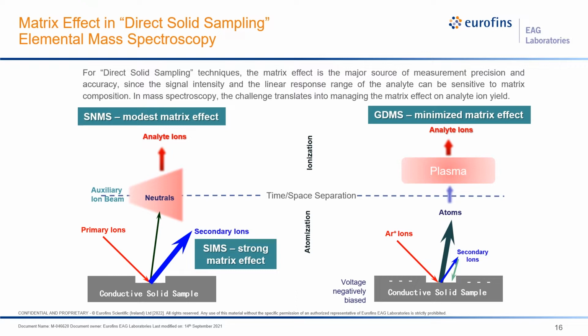Here are the three scenarios. The first case is SIMS, which uses a primary ion beam to sputter a sample and collects the secondary ion yield. As you can imagine, because the ion signal is directly generated from the matrix itself, it generally shows a strong matrix effect. In EAG, we use thousands and thousands of standards to establish precision and accuracy. The second technique, sputtered neutral mass spectroscopy, collects information on both secondary ions and some neutrals. In this case, it exhibits a modest matrix effect because there is atomization and ionization separation, and this allows part of the analyte to be infinitely diluted in the plasma before it is analyzed.